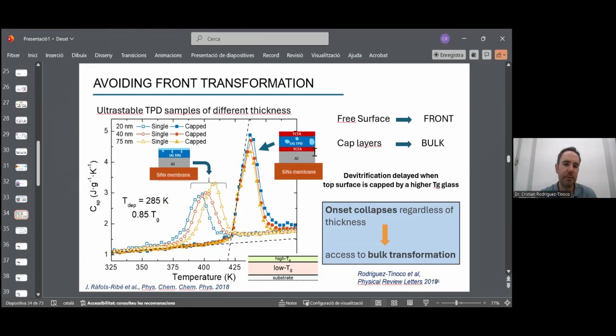If we now do the same, but capping this glass that we want to study with a higher TG material, so TPD capped with TCTA, we have this devitrification temperature for samples of different thicknesses. You see 20 nanometers, 40 nanometers, 75 nanometers, all of them have the same devitrification temperature regardless of the thickness, which means that indeed, when the glass is capped with a higher TG glass, we have a bulk transformation. And this is how we can access bulk transformation properties.